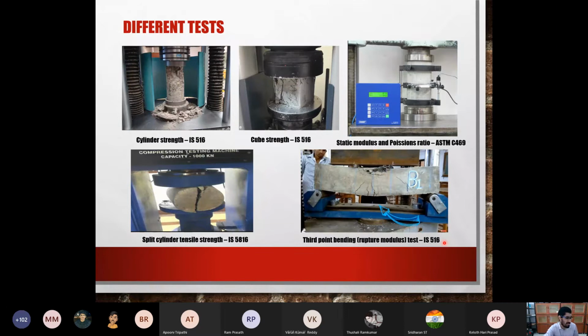Why don't somebody do a UTM test for finding the tensile strength of concrete? Concrete is weak in taking tension. It is best in taking compression loads. It's weak in tension, and the other thing is you cannot actually very easily grip concrete on a UTM. So these two reasons. So if you directly measure the tensile strength, you will get a very low value. It will just fracture wherever you're loading it. Okay, so it will be very sudden and immediate, and you won't get a proper failure pattern.